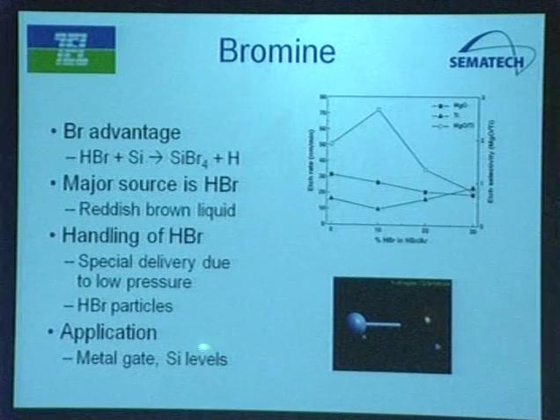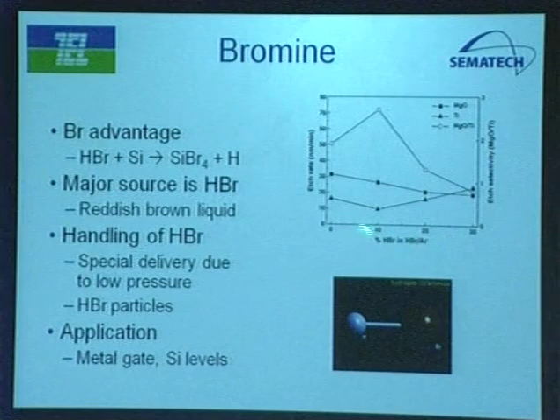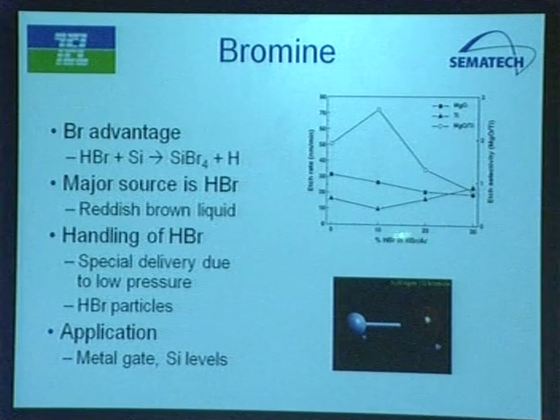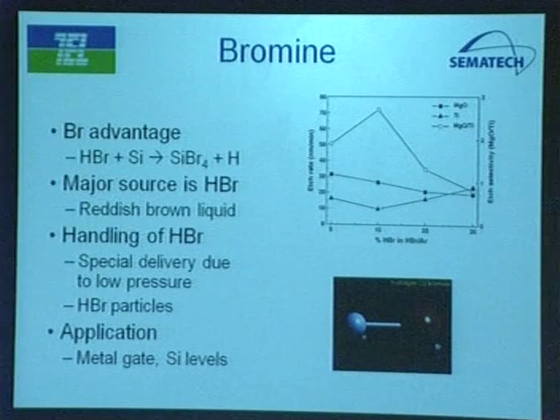Metal gates, all levels of silicon are handled by this. And this gives you an idea, just scratching the surface, about what plasma etch and plasma characterization are. What Alok actually performs is he measures an etch rate of a film. We'll talk a little bit about how that happens. And he varies the amount of HBr in a plasma, where we have HBr and argon here. As you increase the amount of HBr in this plasma, you see that you actually get a peak in what we call etch selectivity between these two films. And those kinds of things are very important to know when it comes to setting up a process to actually build transistors.